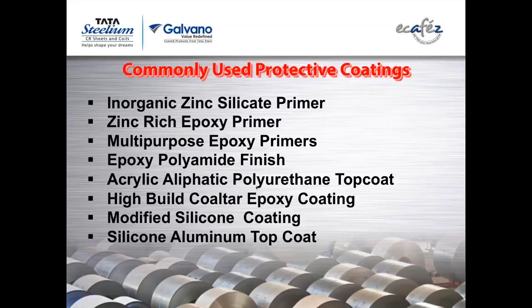Usually, in such cases, they sprinkle water onto that and the curing happens here. This primer is also very good. This can withstand very high temperatures, 250 to 300 it can definitely take care of. Then zinc rich epoxy primer. This comes as epoxy base, epoxy hardener, then zinc powder separately and thinner. So again, very high protection.